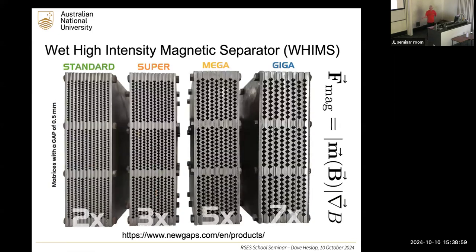And in fact, in some separators, they really play on the field gradient part. So this is what's called a WHIMS, a wet high-intensity magnetic separator, and they generate the magnetic fields within these magnetic cores, and because they're all spiky and they've got these irregular shapes, they can generate really strong field gradients. So they pump up this term here, and therefore increase the attractive force. So there's different ways of approaching this. Of course, there's some very clever engineering that's gone into building these systems.